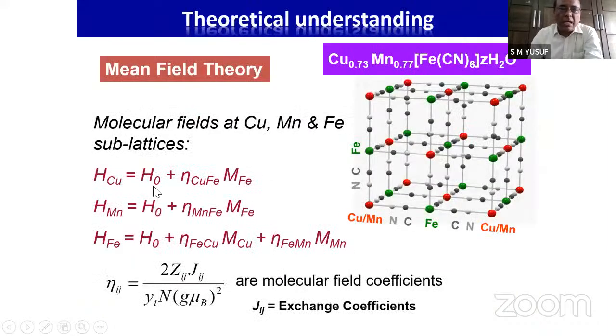Here is the crystal structure. You see the magnetic atoms sitting at the corners. This is a double perovskite kind of structure, with the magnetic atoms bridged by nitrogen and carbon atoms. The internal molecular field seen at the copper site can be written like this. Similarly, for manganese it can be written like this, and also at the iron site.